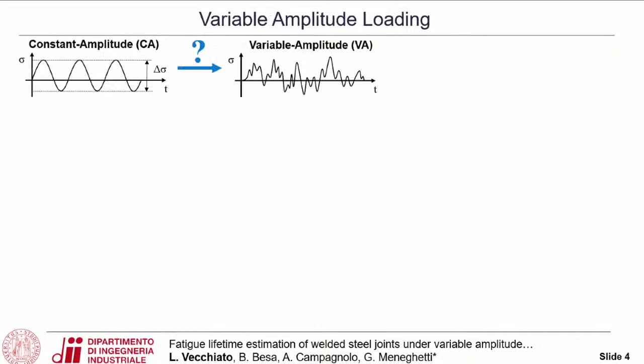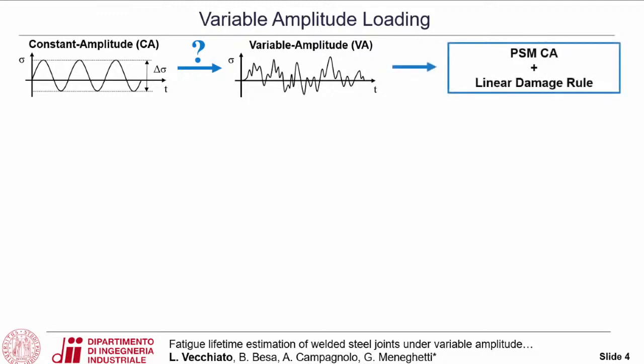In this context, the aim of the presented work was to try to extend the formulation of the peak stress method not only for constant amplitude loading, but also for variable amplitude loadings. And to do so, the idea was to preserve the simplicity of the method, and it was chosen to combine the peak stress method formulation for constant amplitude loadings with a linear cumulative damage rule as proposed by the Eurocode 3. The consequent procedure is quite simple to apply and preserves the simplicity of the method, also shown by my colleague Alberto Visentini.